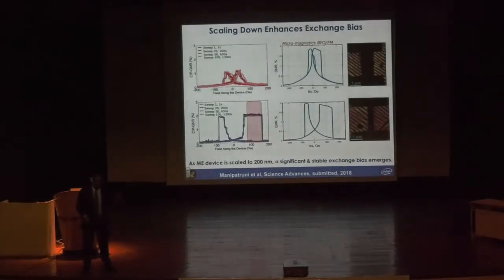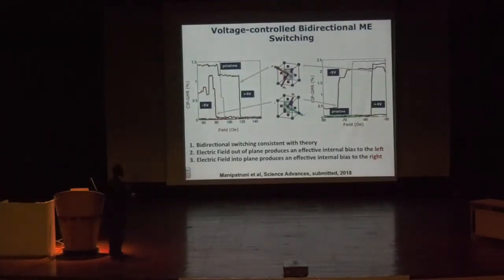So we were seeing something which we had never seen in our previous Nature paper. Sashi has now submitted it to some journal for publication, that there's a strong exchange bias. For a device that we're going to chat about in a minute, this exchange bias happens to be very important. Okay, and what he also showed, in these beautiful measurements, is that you have bidirectional switching of the magnetization in the spin valve, very consistent with Jorge's theory. The electric field out of plane produces an effective internal bias to the left and vice versa to the right. And you can see that the red curve and the green curve, the pristine data is here, are flipping directions as I go with -5 and +5.